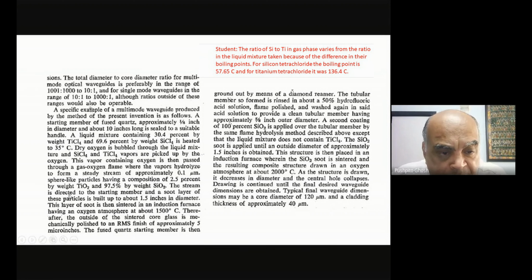Okay, so the stream is directed to the starting member, and a soot layer of these particles is built up to about 1.5 inches in diameter. So from something like 1/8 inch, which is the initial thickness of the rod, they're building up the thickness to about 1.5 inches in diameter. Okay, so a huge amount of soot is actually being applied. This layer of soot is then sintered in an induction furnace having an oxygen atmosphere at about 1500 degrees C. So that's what they're doing.